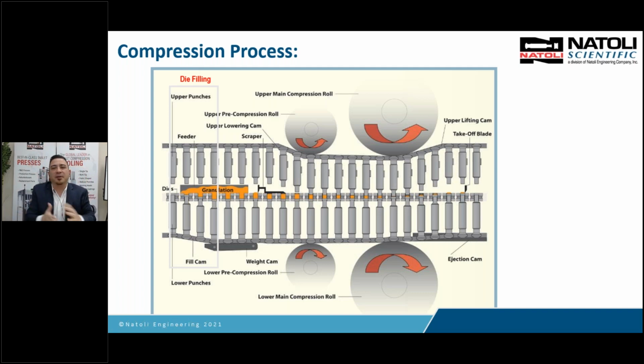There are 2 major types of feed systems. There's gravity feeders and there's paddle feeders or force feeders. You'll notice here, here's our feeder and it says granulation on it. The fill cam is a lower cam that's going to start this process. What the fill cam does is pull that lower punch down and create a partial vacuum with that tight clearance between the lower tip and the die cavity. So when it pulls down, it creates a vacuum and hopefully there's material above it, so it sucks in material.